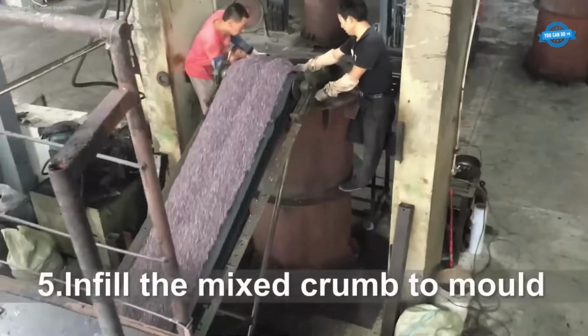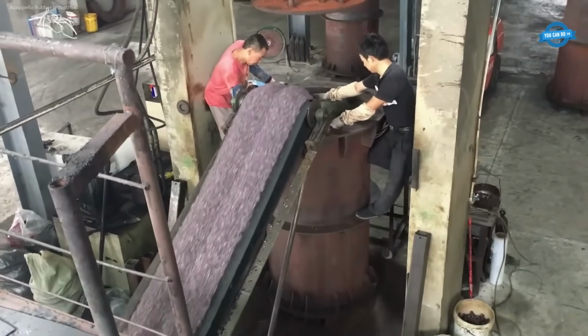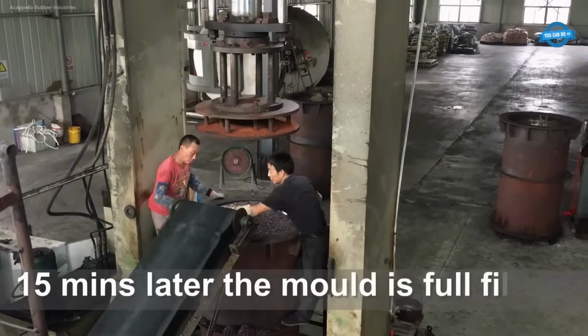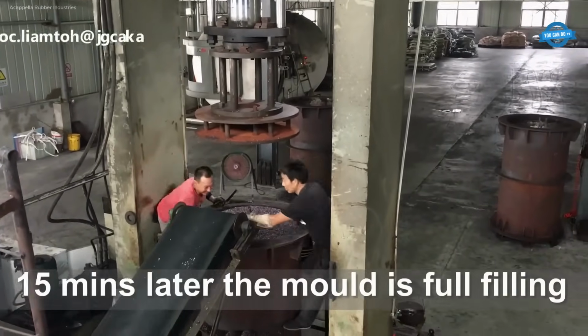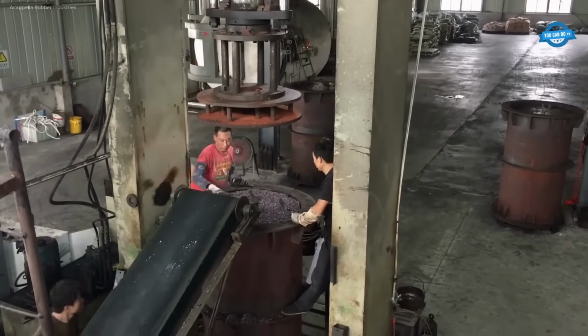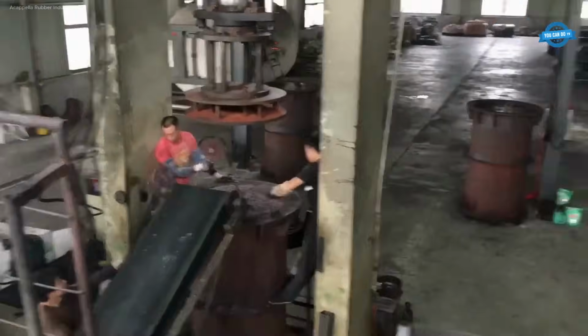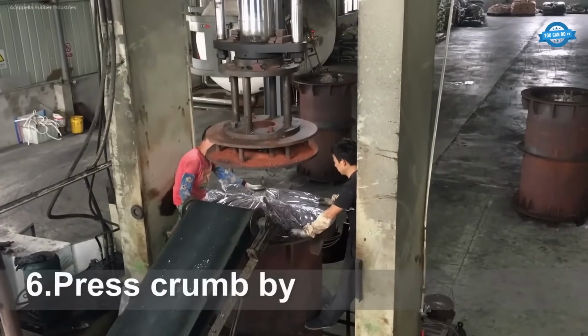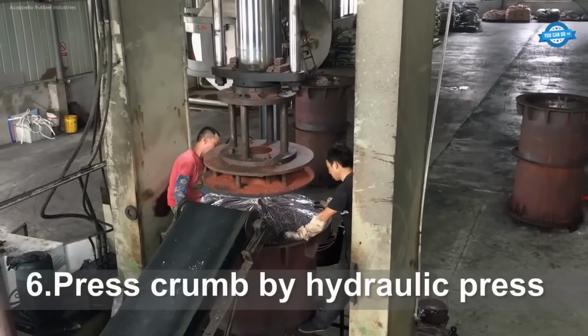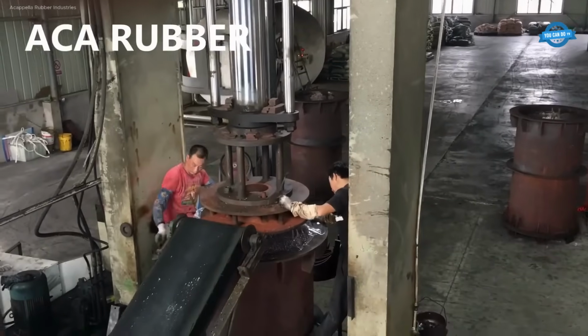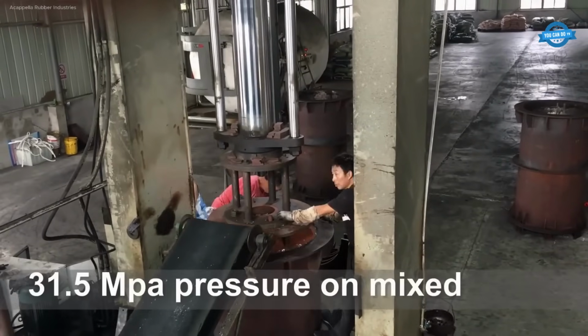In the mixing process, 8 kilograms of rubber crumb are combined with 1 kilogram of polyurethane binder. The mixture is blended thoroughly for about 8 minutes to ensure an even and consistent distribution of the binder throughout the crumb material. Uniform mixing is essential to guarantee the final mat's durability and performance.